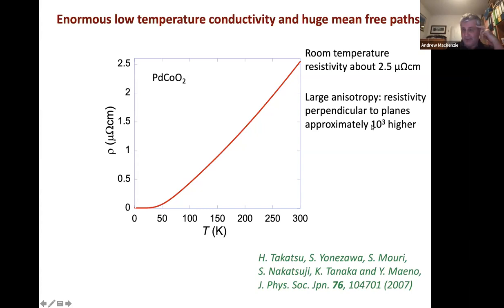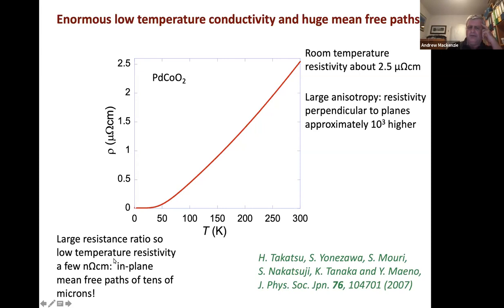But they also have very good resistance ratios, so that when you've taken palladium cobaltate down to very low temperatures, the low temperature resistivity is only a few nanoohm centimeters. And if you use the known Fermi surface to deduce a mean free path, that estimate is tens of microns for the best palladium cobaltate crystals. And for anybody with experience in metals at low temperatures, that's already a very, very high number.